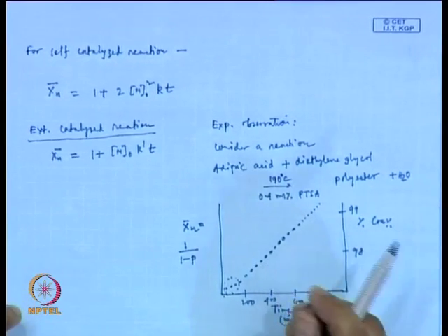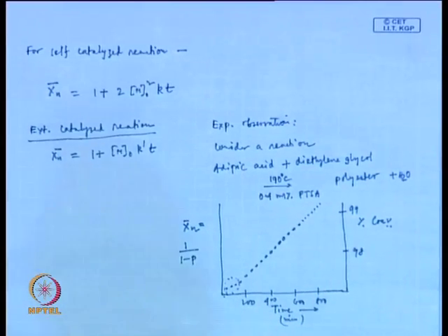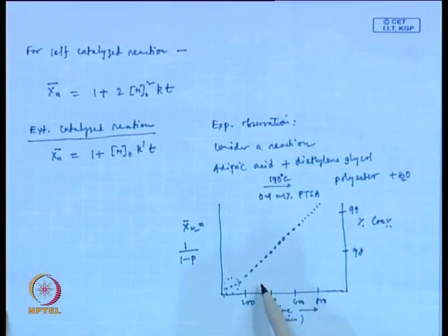So, even if at high conversion the length of the polymer chain or the oligomer chains are quite high, the reactivity of the functional group residing at the end of the chain is the same as when the conversion was smaller. That means the size of the polymer chains was smaller. Remember, what are the other conditions we have assumed or imposed during the derivation of this expression?